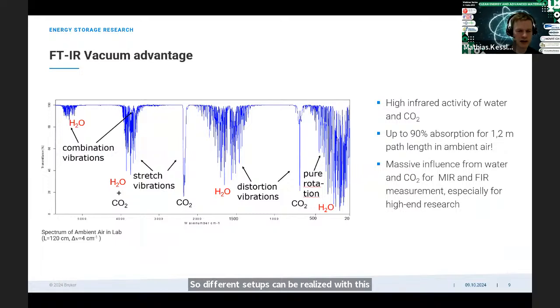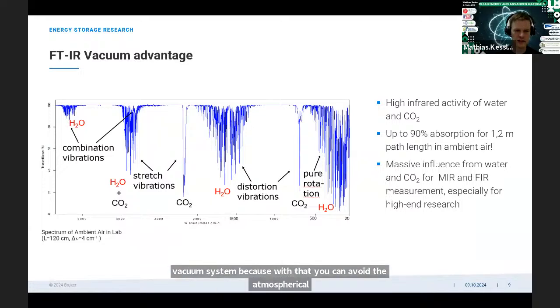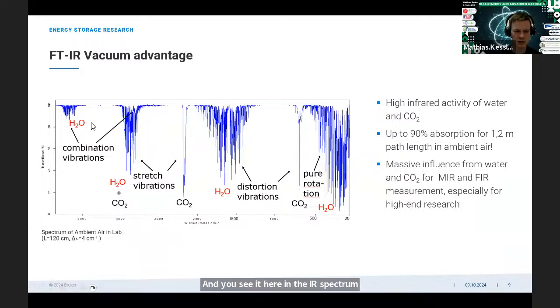And one important thing I want to mention in addition, of course, the best way to do such experiments is a vacuum system, because with that you can avoid the atmospheric contribution. And you see it here in the IR spectrum. This is the spectrum of water vapor and CO2. And both gases show very strong absorption in the middle infrared, so in the fingerprint region, and of course also in the far infrared, but the middle infrared is the most interesting part for our battery research investigations. And if we use a vacuum system, then we can avoid this contribution, and we have a perfect baseline and a very low noise and a high signal to noise ratio is then possible.